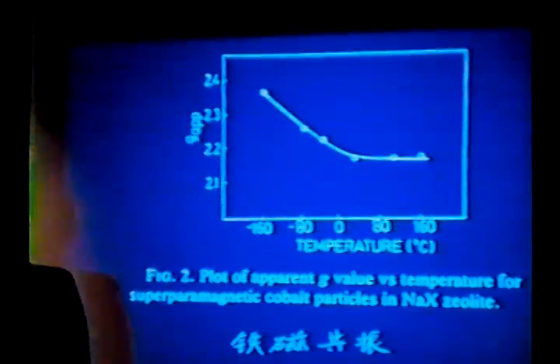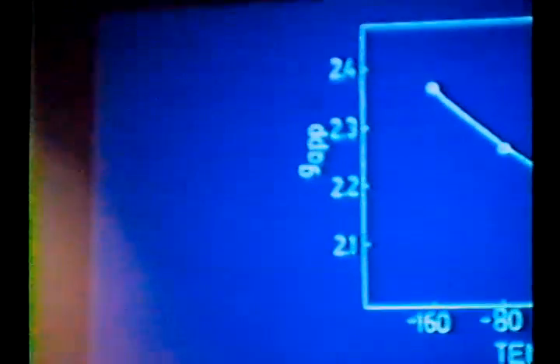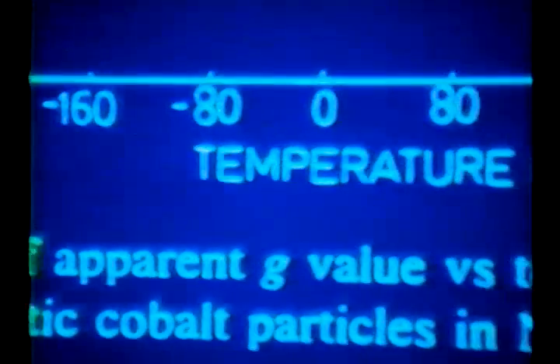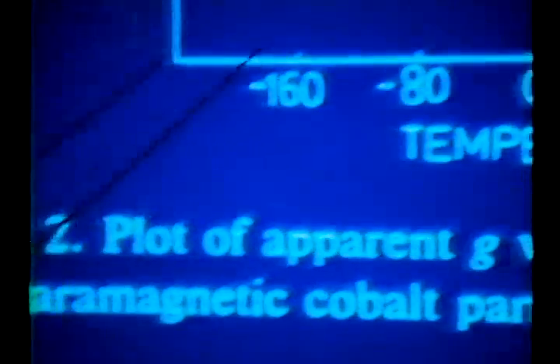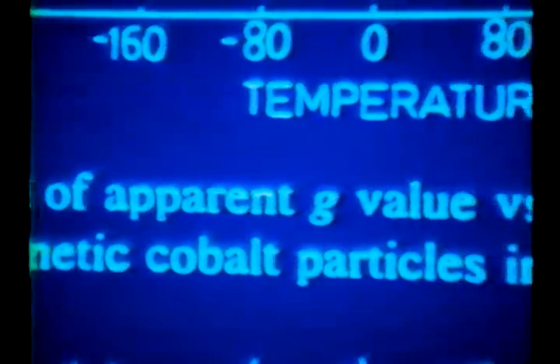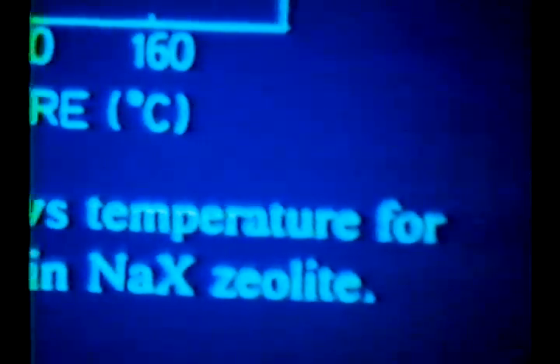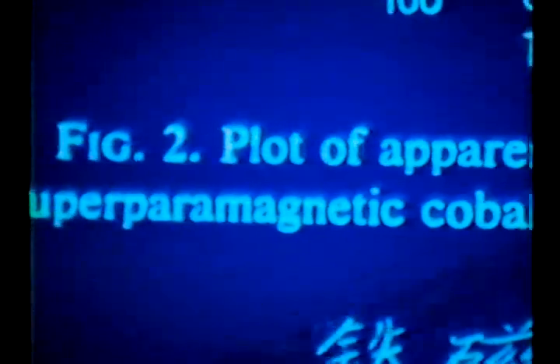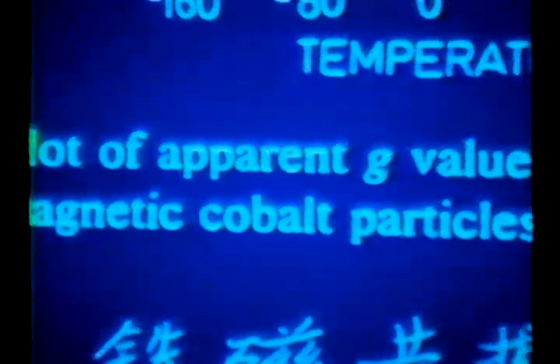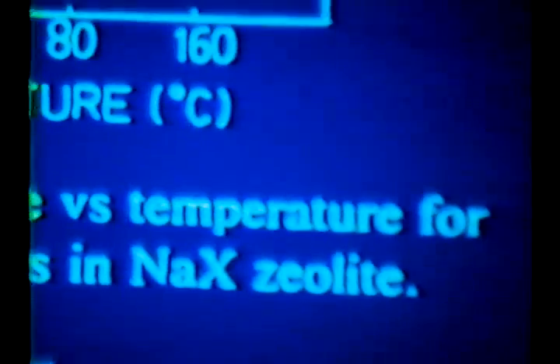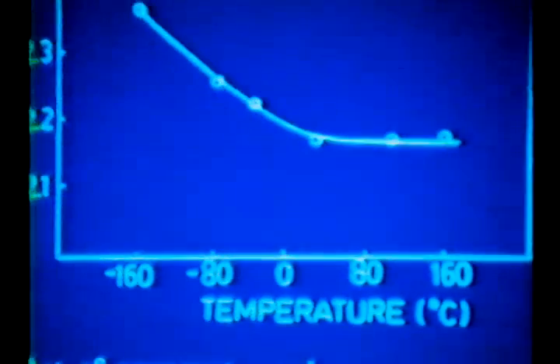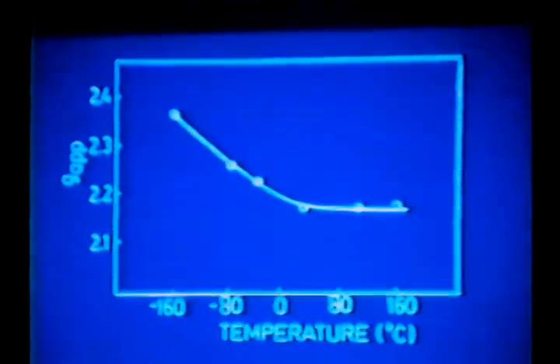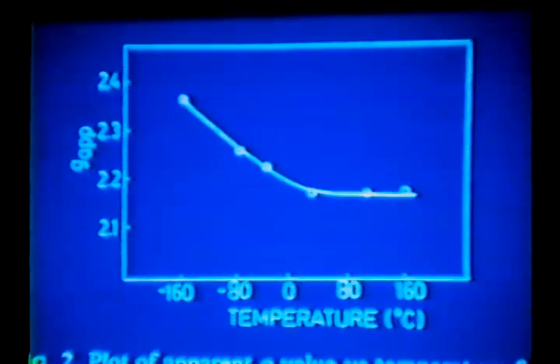Well, ferromagnetic resonance is the second technique I wanted to talk about. Basically, that can be used to look at oxidation states in the material, to look at whether the material is ferromagnetic or not. And this is a plot of the g value, where the signal occurs, as a function of temperature. And if you look in the literature and go through the theory, basically what you can show is that for very small particles of cobalt, they should have a g value of 2.18. And the lower the temperature at which you observe this 2.18 value, the smaller the particle.